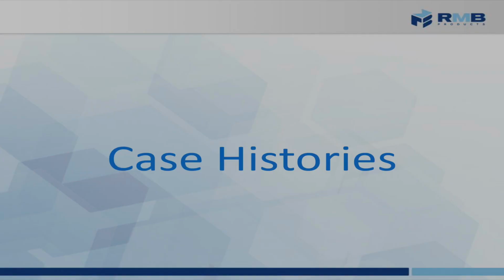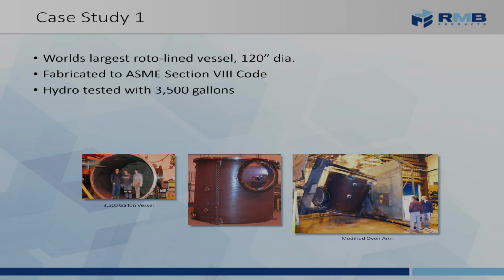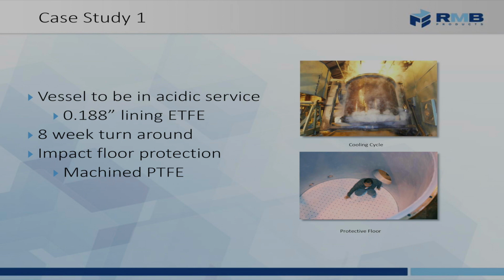So some case histories. This is actually the tank that I showed rotating earlier on. It was 10-foot diameter, ASME Section 8 code, 3,500 gallon. And this was an ETFE lined, 3/16 thick liner, done in 8 weeks. In this case, there was this impact floor protection made of PTFE in the bottom. So that is an example of what the cooling cycle looks like.